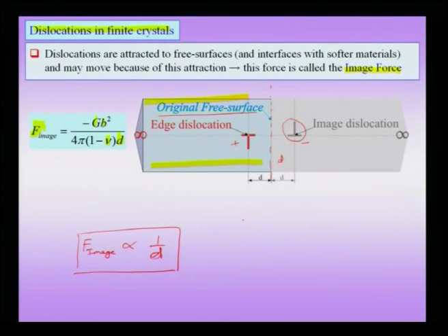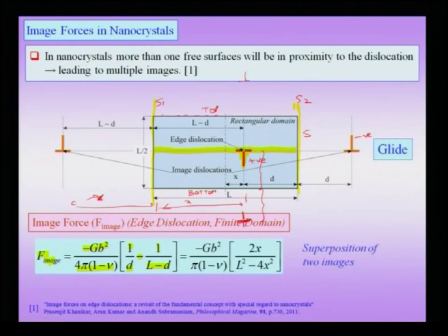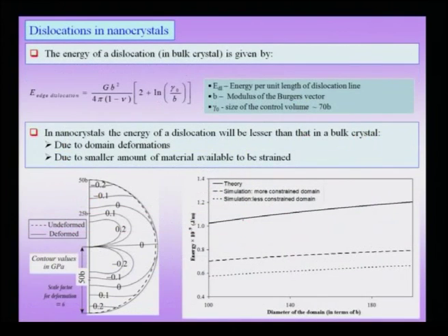And it is important to note that in the case of a bulk crystal, if the dislocation is far away from the free surface, the force will be too small and I need not worry about it, while in the case of a nano crystal I cannot ignore the images, because the dislocation is going to be in proximity